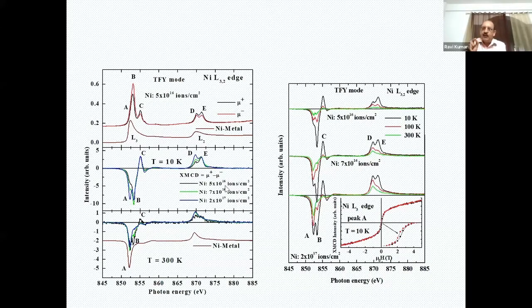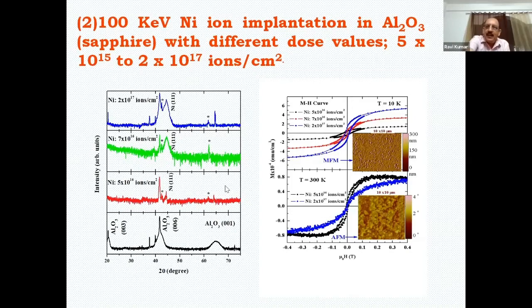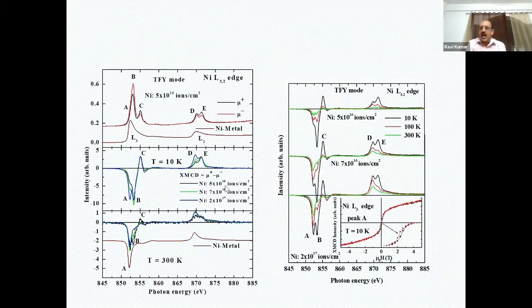Now, we again formulated the magnetization curve using the XMCD signal. And this signal is clearly matching with the signal obtained by the SQUID magnetometer. So that's why I have demonstrated we can embed that. These kind of magnetic nanostructures embedded into the system have many applications. They can be used as memory devices. They can be used as a single electron transport system also. Those I will not discuss here because those are a little bit different arena in the present case.